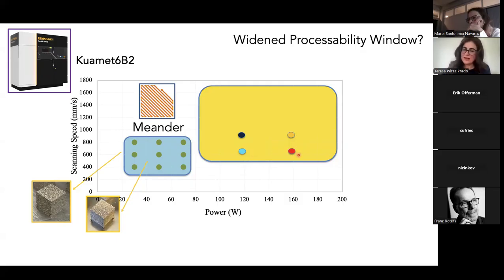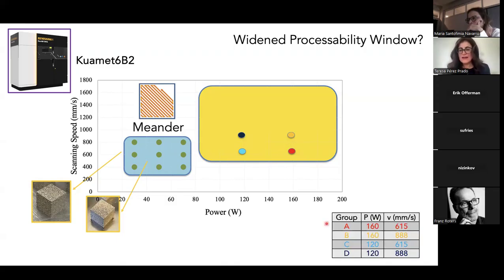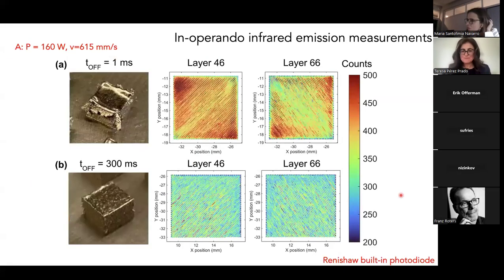Because of course, if we use higher laser powers, it's well known that we very likely will have better density, but we need to be able to really work here. So we chose 4 conditions within this, up to now, forbidden region. This is what I call these groups, A, B, C, D. A, red, is the highest volumetric energy density. D, which is the dark blue, is the lowest volumetric energy density. And we applied different time delays to all these 4 groups, ranging from 1 to 300 milliseconds. So let us see what happens.